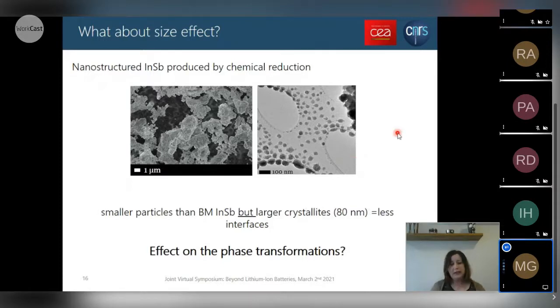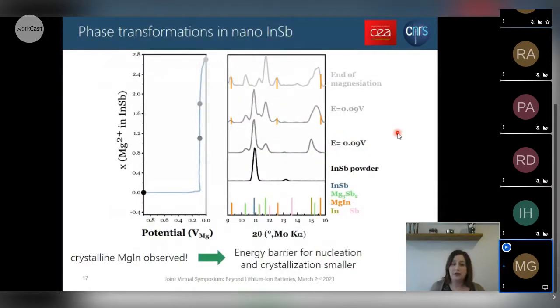In a similar way, we looked at ex situ X-ray diffraction data at different points of magnesiation for this nanostructured InSb. And as you can see, we still see the formation of Mg3Sb2 and indium. And interestingly, starting from the middle of the magnesiation to the end of the magnesiation, we clearly see the formation of crystalline MgIn here. So by changing the morphology of the particles and the crystallite size, we have changed the energy barrier for nucleation and crystallization, and this leads here to the crystallization of the MgIn phase.